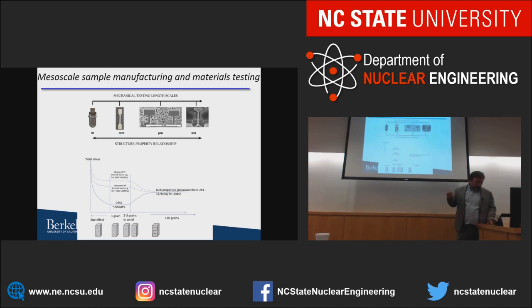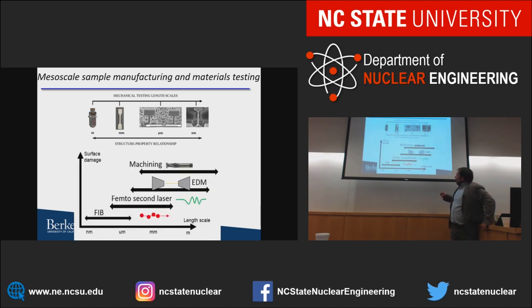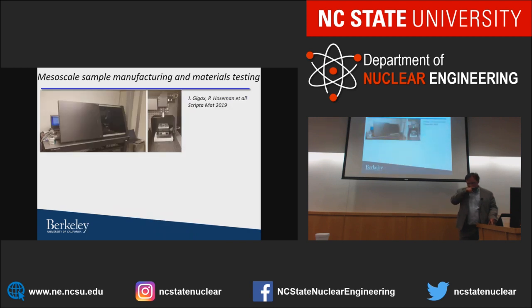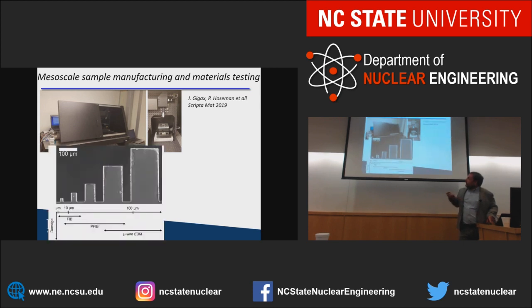It turns out you can do big samples, in this instance millimeters. You go milling and machining and all that sort of thing. And you can do the nanoscale stuff doing fibbing, right? Focused ion beam machining. In between, there's really only one or two methods you can use. And recently we looked into these femtosecond laser machining tools, which allow us to make 20, 30 micrometer diameter samples, which you can't really make any other way. So about 6 months ago, we purchased from a NEUP infrastructure grant this femtosecond laser ablation tool, and used that to make, for example, pillars.